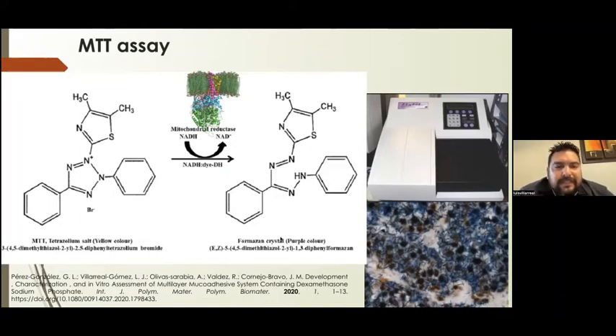To do this test, we expose the cell lines to the fibers for 24 hours. After these 24 hours, we take apart the cells and then we add the dye. So we then wait for 4 hours, and if the cell is alive after being exposed to the fibers, the mitochondrial enzyme will work very well and will create a high concentration of formazan.